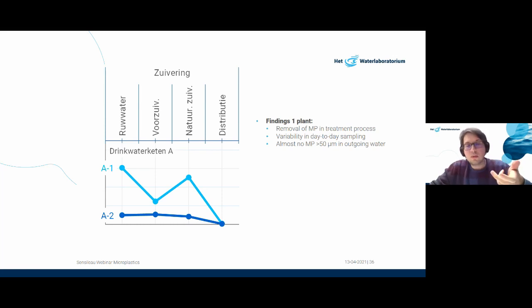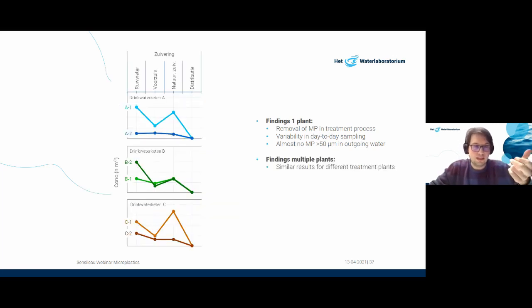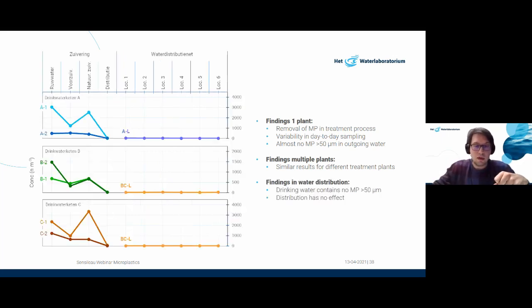Eventually we also found that there were almost no detectable plastics in the outgoing water. We did the same thing for 3 different production chains, and we saw the same results for all of them. And then when looking at the distribution, so at the water that basically runs out of your tap, we saw basically a flat line, meaning that we didn't really find any differences between the outgoing water and the water you receive. So it seems that the distribution didn't have a lot of effect, or at least not in this range, because, as I should note, and as also written on the slides, we're only able to analyze microplastics larger than 50 micrometers. So we're talking about the relatively larger portion of microplastics, and not at all about the nanoplastics.